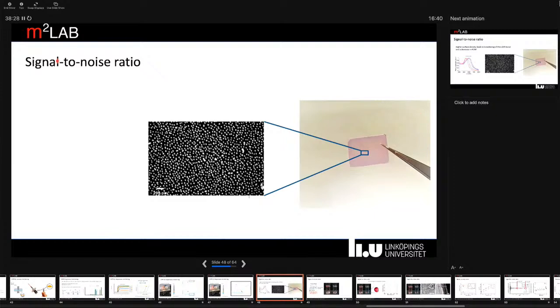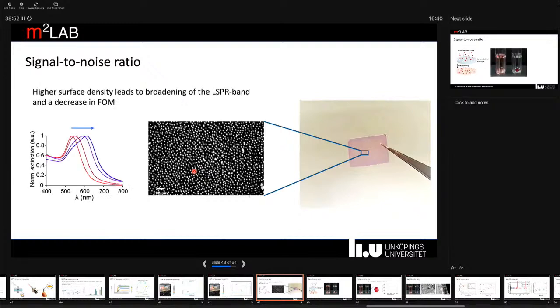This is a photograph of a glass substrate that has been functionalized with gold nanoparticles. And you can see this faint pink color comes from the particles. And here we actually have a fairly high density of particles. You can, of course, squeeze in more particles there. It's definitely possible. But then this starts to happen, that we get a broadening of the plasmon band and a redshift. And that has a negative impact on our figure of merit and the sensing performance. So we can't really improve the signal intensity by just squeezing in more particles here.